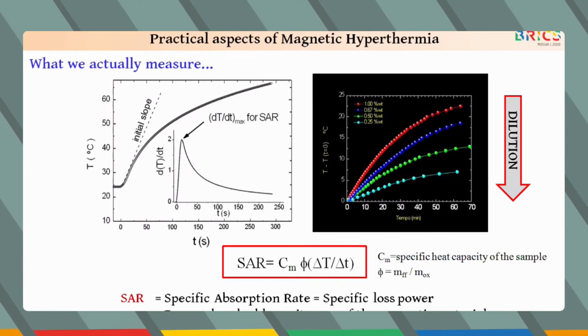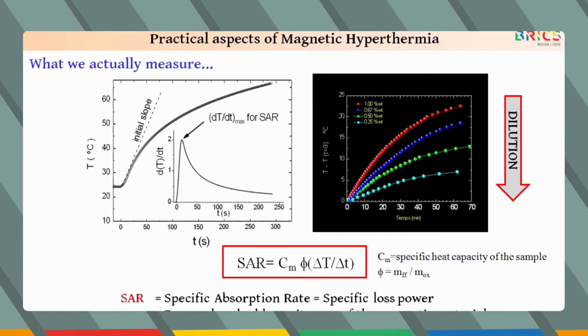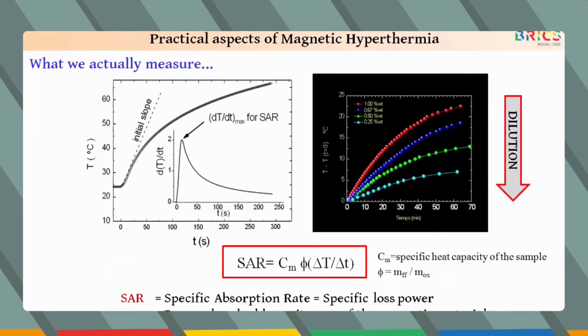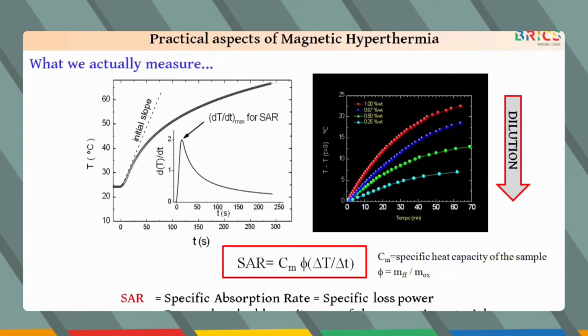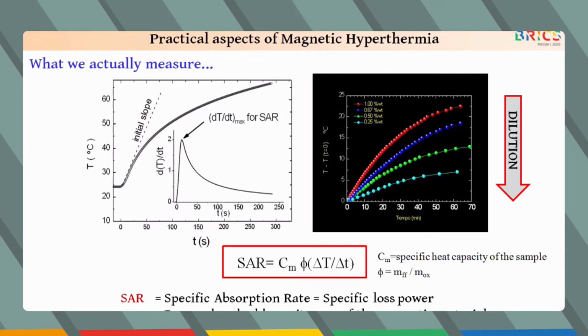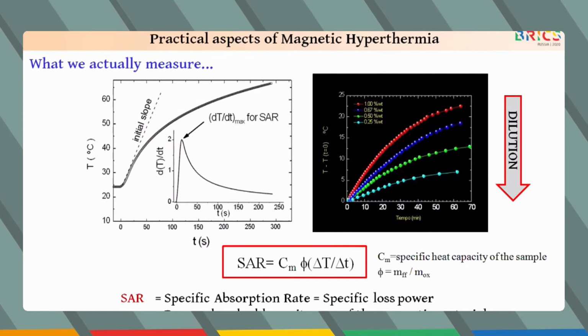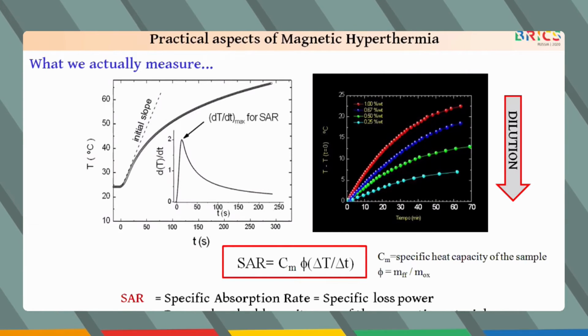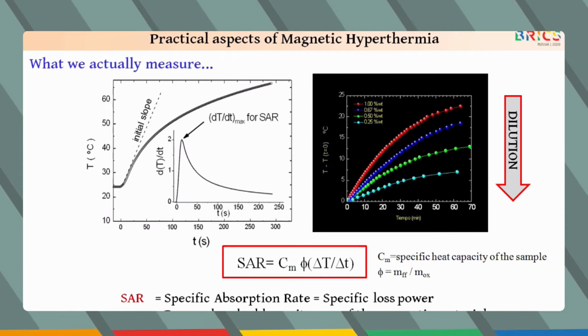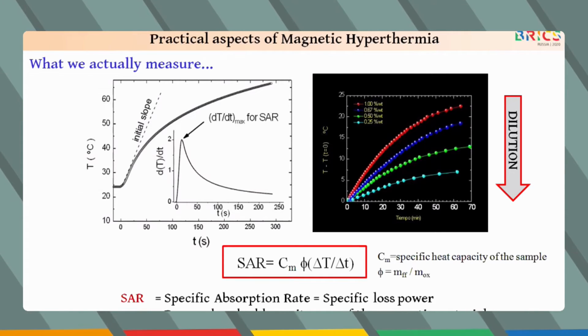A higher concentration of magnetic nanoparticles will lead to a greater amount of heating during magnetic hyperthermia, as shown in this graph. However, increasing the concentration of nanoparticles may lead to increased toxicity and other undesirable side effects. So understanding the heat flow from the magnetic nanoparticles into the surrounding tissues, and then through the surrounding tissue, will be important when designing specific applications.